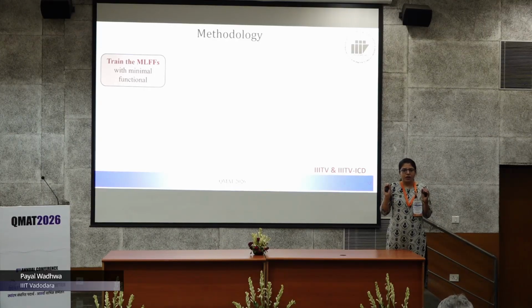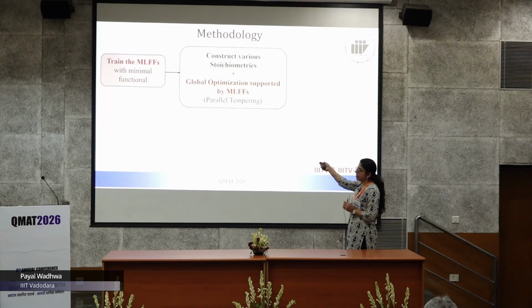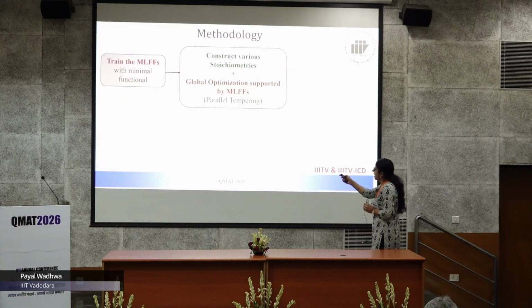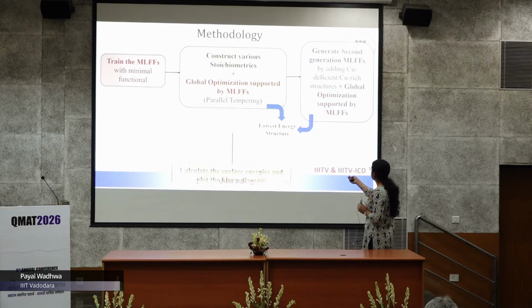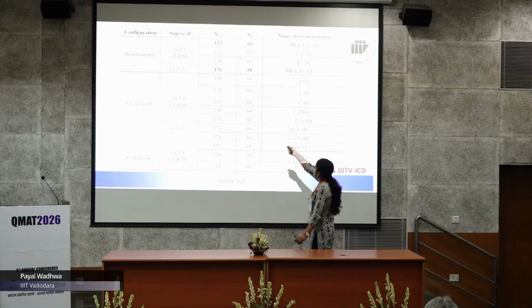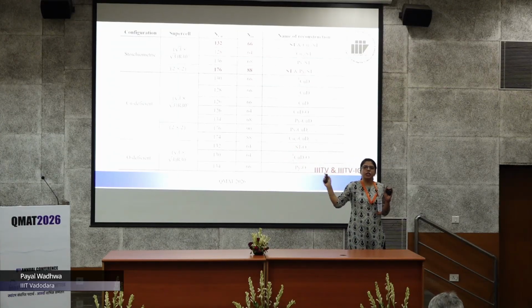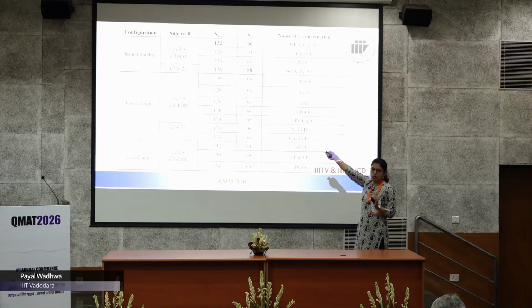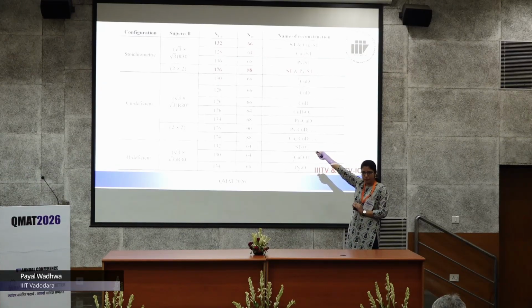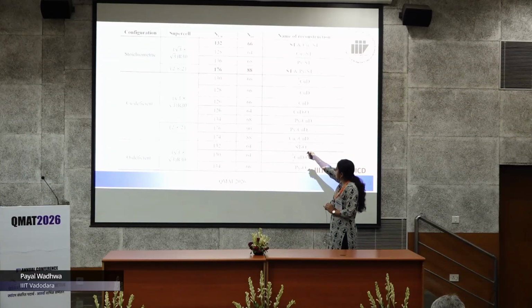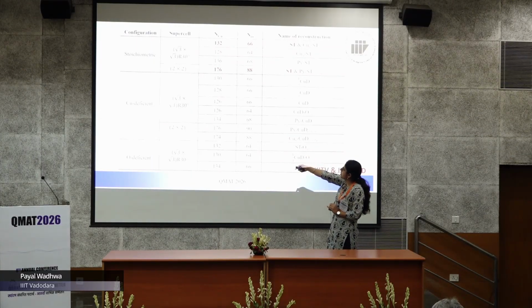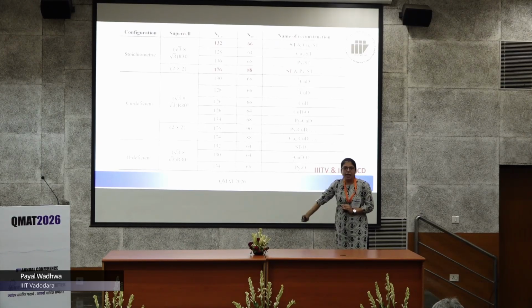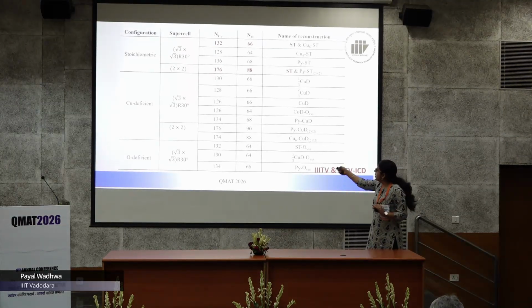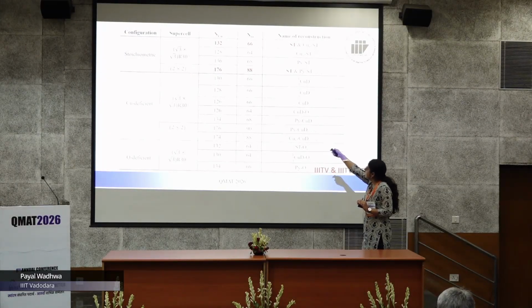So the methodology we followed: we trained the force fields on a stoichiometric structure with the minimal functionals. Then we constructed various stoichiometries and performed a global optimization algorithm, parallel tempering, driven by the machine learned force field. What I'm trying to say here is, let me go to this slide. The original stoichiometric configuration means perfect Cu2O combination, like 132 coppers and 66 oxygens. I trained the machine learned force fields on it, and then I constructed various other stoichiometries, meaning other perfect Cu2O combinations or copper deficient or oxygen deficient. Then we performed global optimization on these structures with this force field.